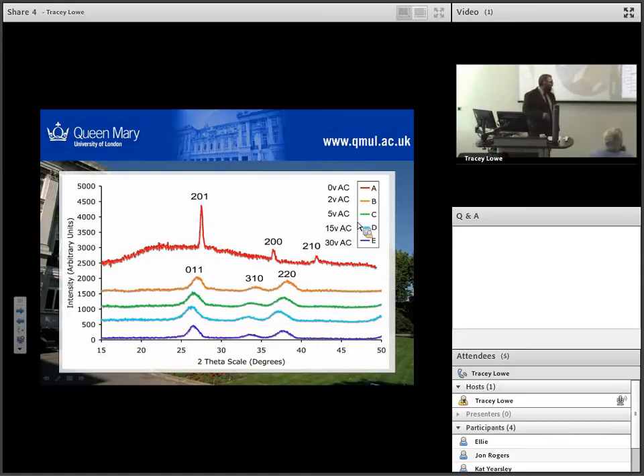Another thing worth pointing out, looking at the X-ray diffraction patterns: with our standard deposition we see growth in the usual monoclinic space group, with fairly sharp peaks. When we grow with an electric field, the first thing is that we're crystallizing in a slightly different monoclinic space group, one that's normally associated with doping. Our peaks are getting broader, indicating a smaller crystallite size, and there's some change in peak position, indicating a change in our lattice constants.